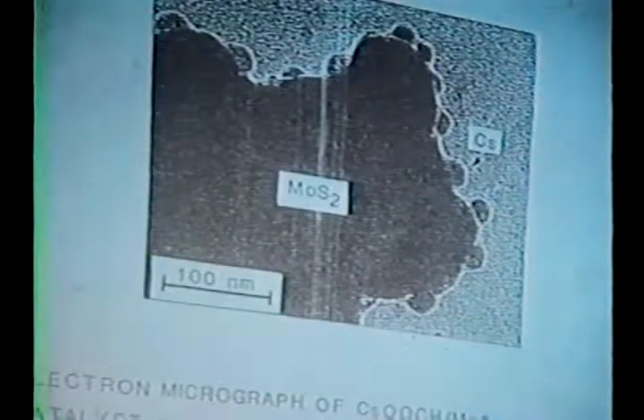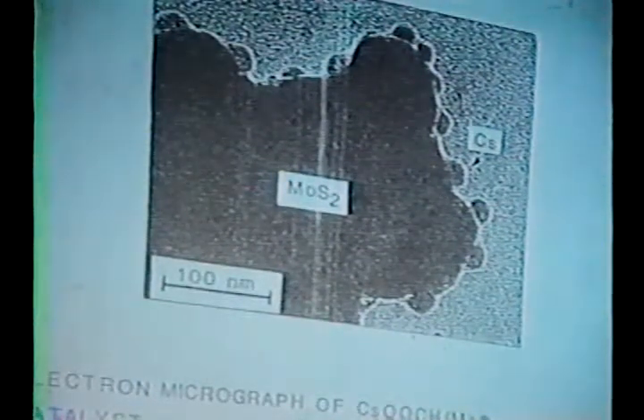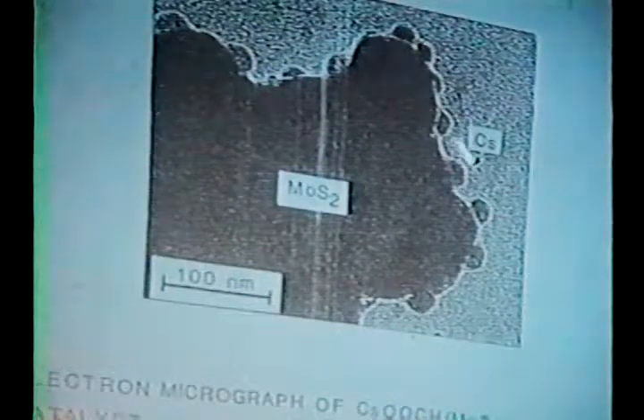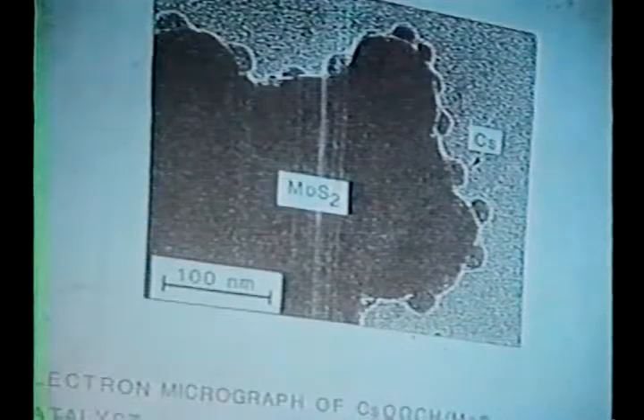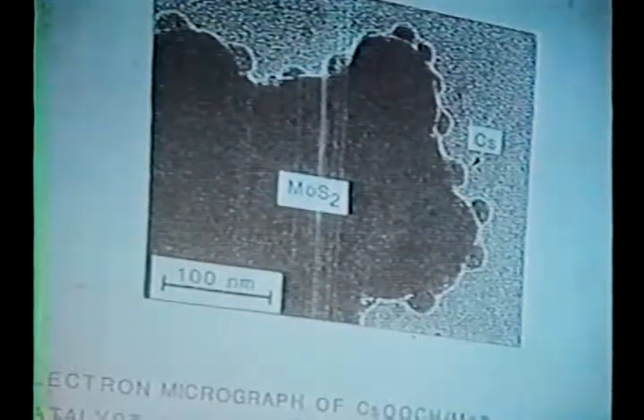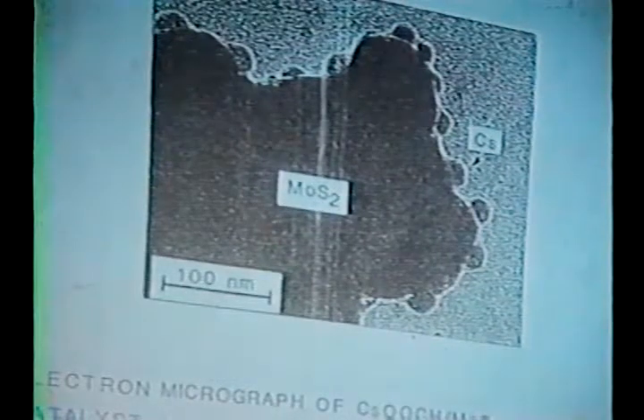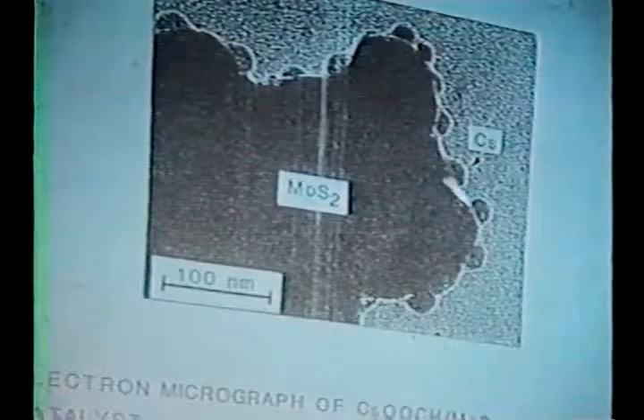The catalysts are pre-treated at temperatures which are above the synthesis temperature, and you actually go through the melting point of the cesium compound at 270 degrees centigrade. So this is a catalyst that has been molten, and the cesium sits on the moly disulfide this way. The interesting question that appears here is: why don't these cesium particles agglomerate at all? And that's a colloid chemistry question, and actually an intriguing one, because the thermodynamically stable situation would be one in which the cesium would be making one big blob.